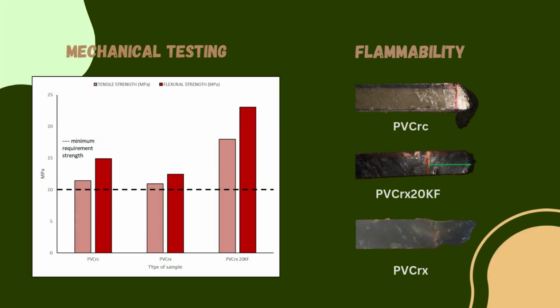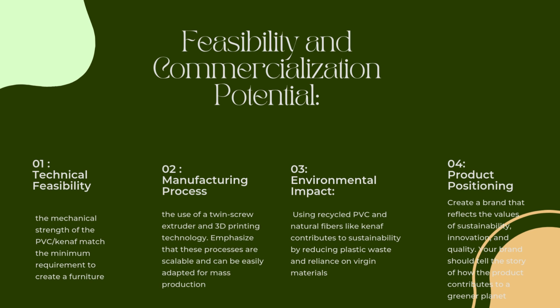We've compared the tensile and flexural strength of our reinforced composite, coded as PVCrx20KF, to other variations, the control and also with additives alone. The results are promising. Our reinforced composite meets and even exceeds the strength requirements for furniture, which typically ranges between 10 and 20 MPa. Additionally, all the samples demonstrated excellent extinguishing properties as they self-extinguished within a few seconds.